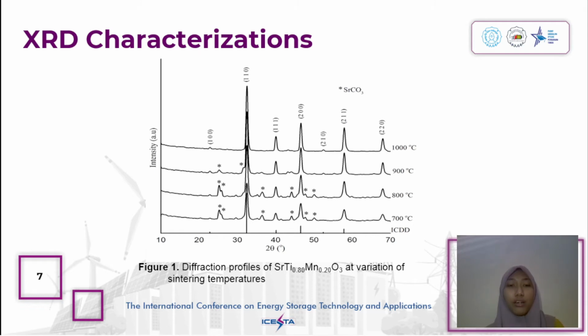The XRD profile confirmed the SrTiO based on ICDD number 8600178. The profile exhibits extra peaks at 700 degrees Celsius, 800 degrees Celsius, and 900 degrees Celsius, according to ICDD number 221437. These peaks correspond to the phase of strontium carbonate. The impurities intensity declines as the sintering temperature gets higher and vanishes at 1000 degrees Celsius. It reveals that the higher sintering temperature provides sufficient energy for the atoms of the material to react completely.